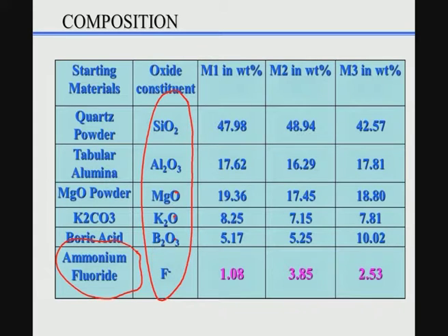Essentially, all these powders as well as their precursors are added in a specific ratio in different glass compositions just to vary the fluorine content, which is varied over 1 to 4%. In this narrow window, we are seeing how fluorine content can give rise to glass ceramic materials with different morphology and with different properties, both physical and biocompatibility properties.